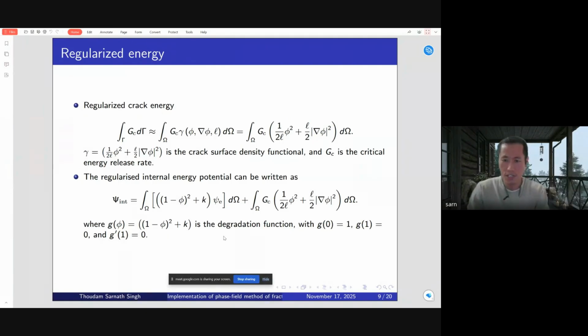And this degradation function has a property that when there is no damage in the material, that is phi equal to 0, its value is 1. And when the material is completely broken, that is phi equal to 1, then this value is 0. So when this becomes 0, the total term becomes 0. And it also has to satisfy the condition that its slope, when the material is completely broken, should be 0. What this tells us is that when the material is completely broken, there is no further degradation in the material. That's why the slope at phi equal to 1 is 0.